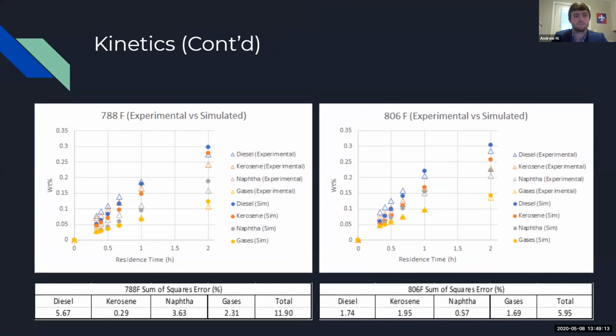And then the middle 2 temperatures, 788, the behavior is pretty much the same as the previous 2 temperatures. But then 806, the naphtha starts to increase as you increase the temperature up to 806. And then again, pretty good fits for both of them. And then for the sum of squares error, 788 is about 12% and the 806 about 6%.